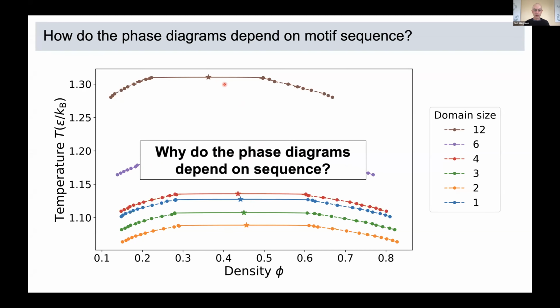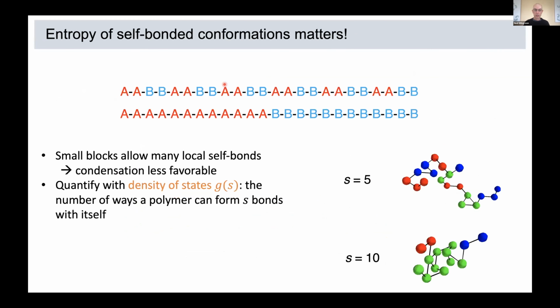So the question is, okay, why do the phase diagrams depend on sequence? And it turns out there's really one dominant factor, at least for this model, and that has to do with what's happening in the dilute phase. What are these polymers able to do when they're all by themselves in the dilute phase? And so what turns out to matter is the entropy of self-bonded conformations.